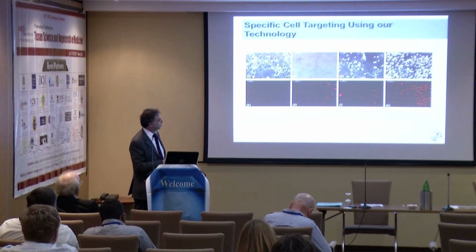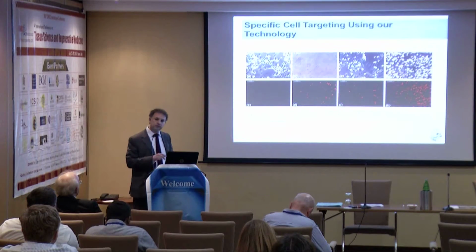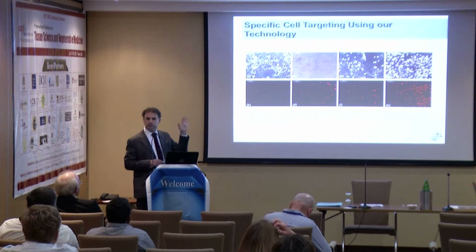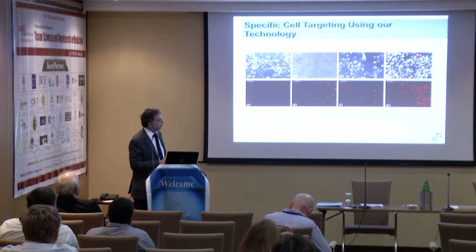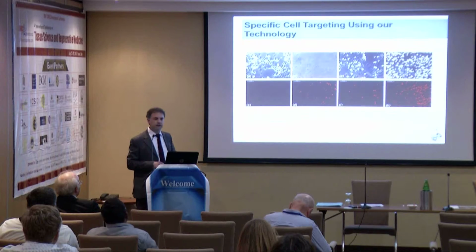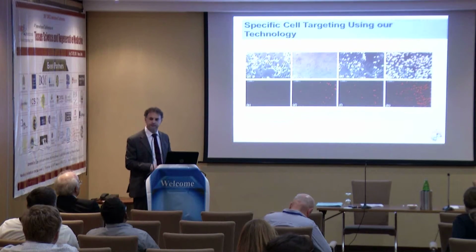You can see that the adhesion is very low, and that could be because the polymers over the surface are a little sticky and recognize some targets on the cell surface unspecifically. But when you put the CD31 antibody that recognizes this protein, the cells attach firmly, and the amount of cells attached over the layer of HUVEC cells increases more than 100%.